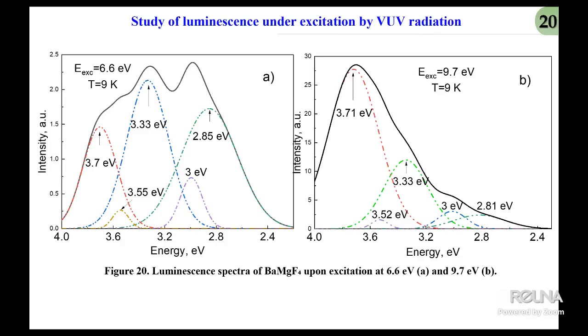This comparison of the spectral and the excitation shows that change in the excitation energy leads to a redistribution of the contribution of excitation and defect centers, which determine the luminescence mechanism of BaMgF4 under both excitations.